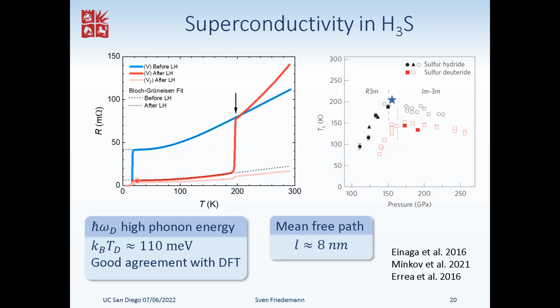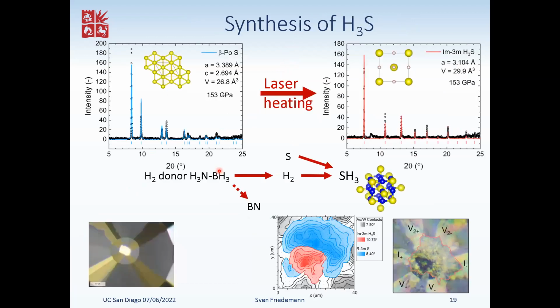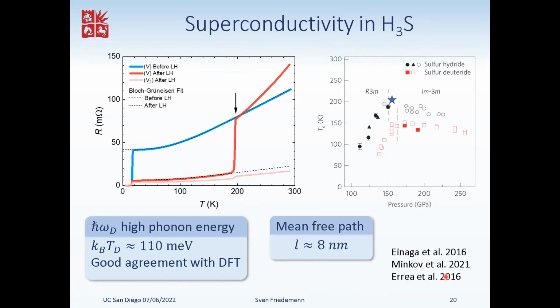So that tells us that this residual resistance is some of the sulfur that's in the current path. That makes sense because we've been probing with these 2 electrodes as current and these 2 as voltage, so probably this voltage lead here is sensing some of the elemental sulfur. But we can understand the behavior of the sulfur quite well.